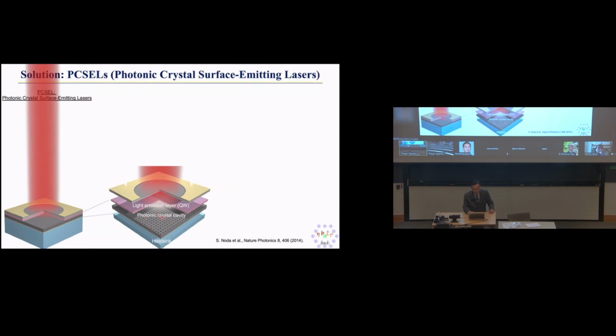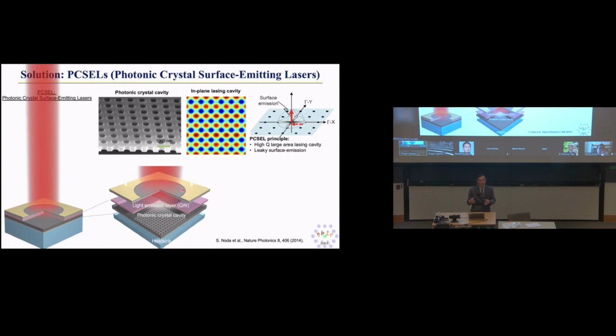And so once we form this nanoscale structure, then we have this light emitting layer next to it. So they're evanescently coupled. I will show you an image later on. Then you form the complete device structure by forming an electrode. So you can do electrical pumping, and they can create a kind of laser cavity here. The operating principle here is this two-dimensional lattice. You can think about it as kind of back scattering. That means light bouncing back and forth whenever there is lattice discontinuity or contrast. Okay, so it bounces back and forth.